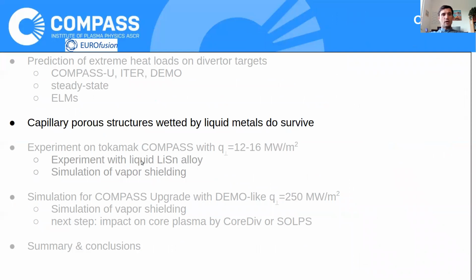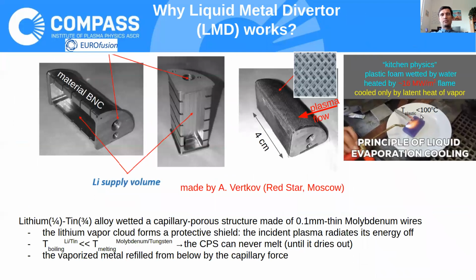So that's why we are interested in capillary pore structures wetted by liquid metals. And here you can see its functionality. The principle of liquid metal is very easy, demonstrated in so-called kitchen physics. Let's take a plastic foam which you have in your kitchen, wet it with water and heat it with a 16 megawatt per square meter flame, which is normally used for cutting metals. And you can see that it's pretty easily cooled by latent heat of vapor, and that's why it never gets above 100 degrees, and so the plastic survives.